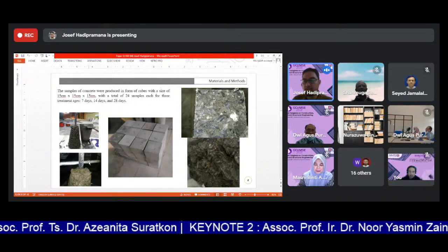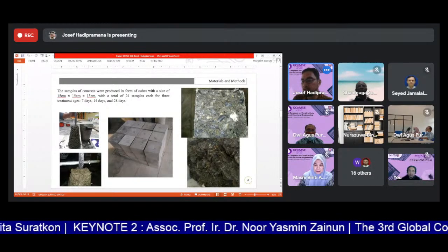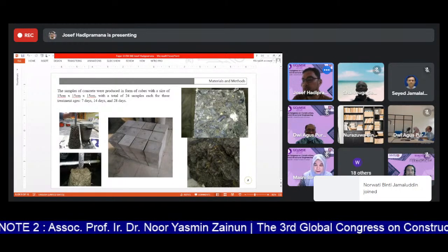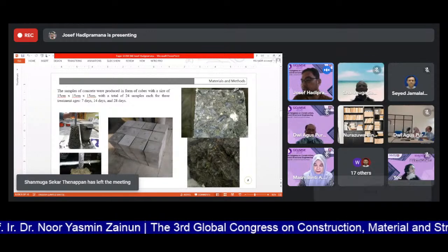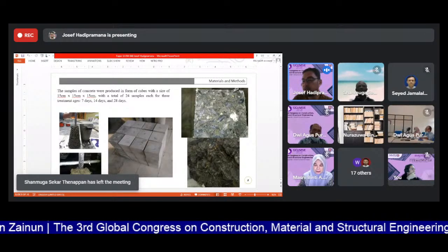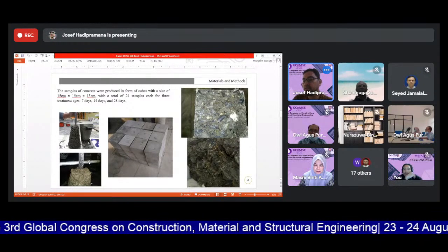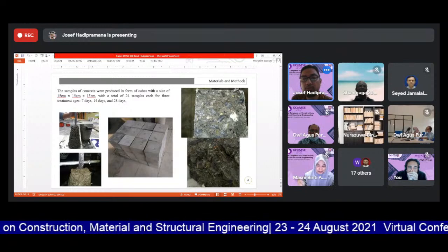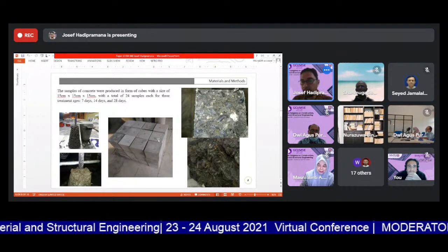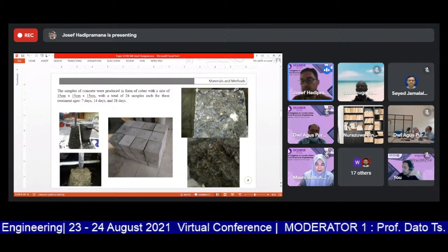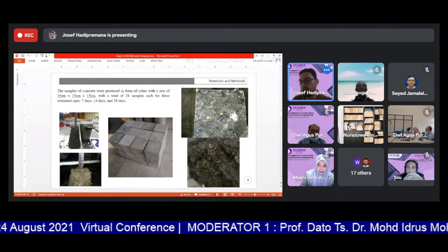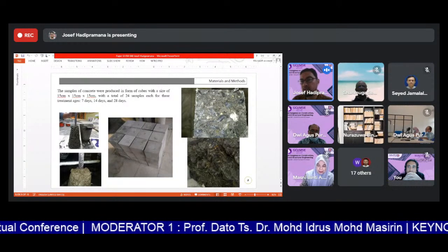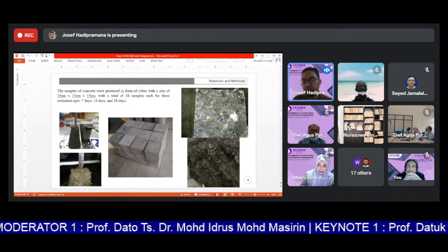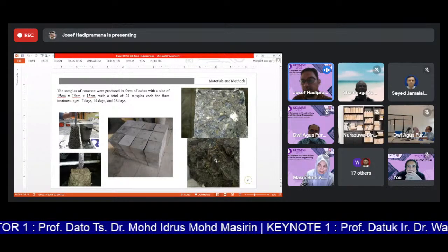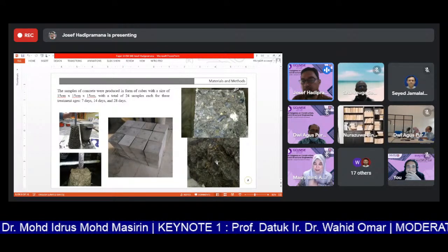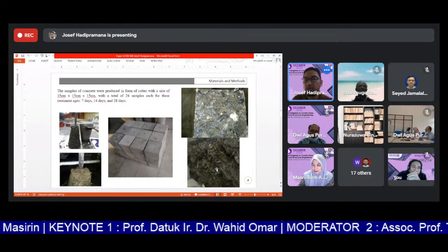So this is the sample of concrete produced, a cube with size 15 centimeters each side. So total 24 samples for each variation for 3 treatment ages: 7, 14, and 28 days. This figure shows the 28th day, where the fiber is not seen again. So the fiber is drowned and bonded to the concrete matrix. On the 7th day, the fiber is still visible here. It's not completely fibrillated.